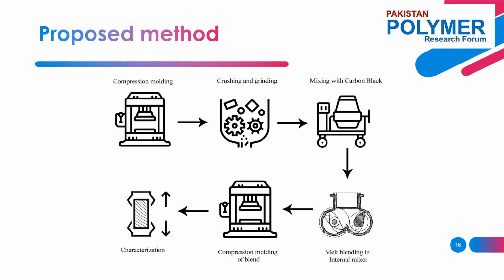compacted in a vertical compression molding to make a thick sheet, because soft fabric cannot be shredded using a small industrial shredder. This hard and thick sheet will be taken to a small scale industrial shredder with high speed sharp rotating blades to reduce the size of the sheet for the next step. In the next step, the coarser particles obtained will be ground in a small high speed rotating blade grinder to further reduce their sizes. The powder polypropylene will be combined with the carbon black nanofiller with the help of sonication in a sealed container at high temperature and pressure to enhance the mixing.